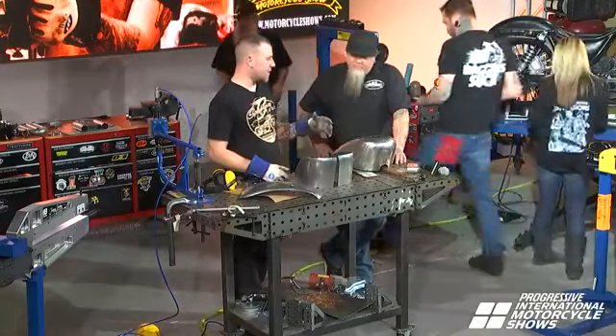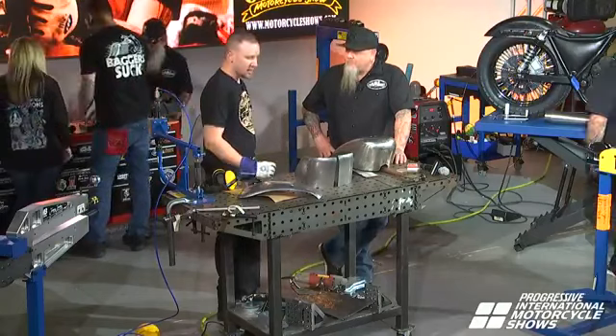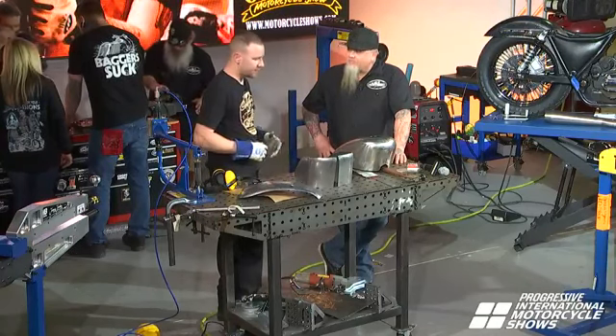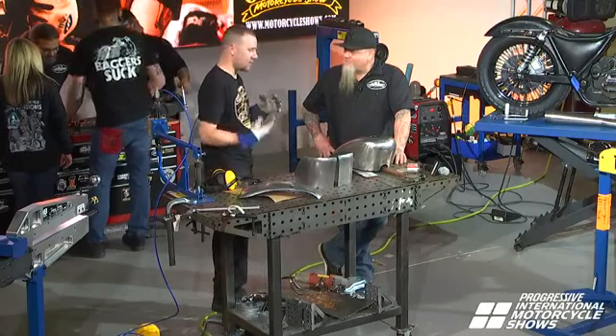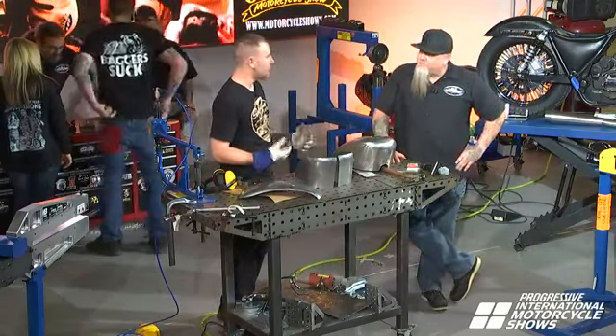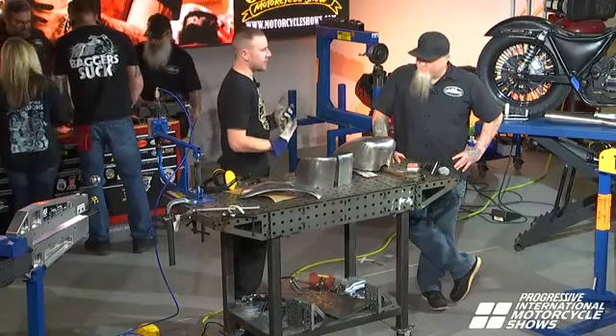A lot of times on those kinds of panels, I'll use die chem, like machinist dye, and spray the whole panel, just like guide coat for bodywork on cars or aluminum work. Then I'll come in with the bastard files, the flat files, and scrape it. All the parts where the dye went away are the highs, and all the parts still blue are the lows, and then I'll hammer and dolly that back out. That process needs to be done before you enclose it into a box, because you need to get behind the panel. It's almost impossible to truly correct a panel if you don't have access to the backside.